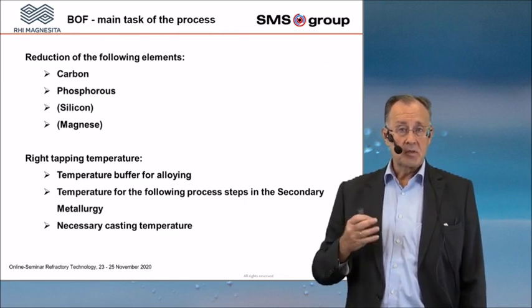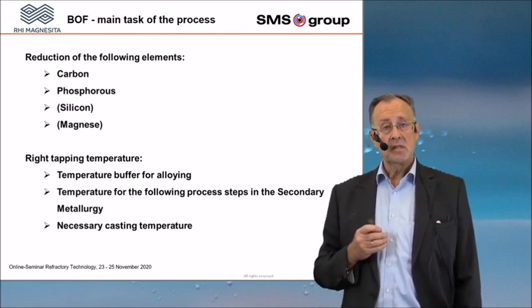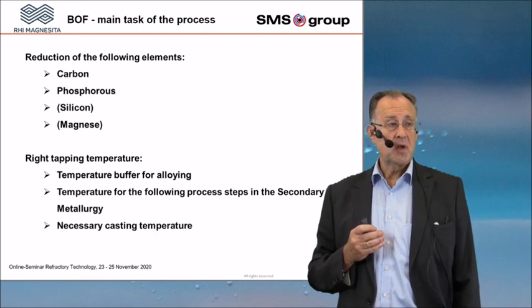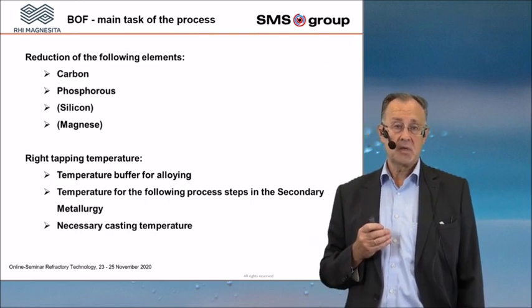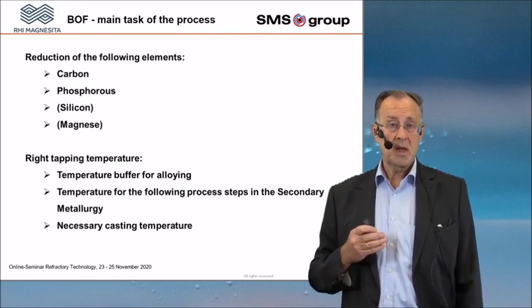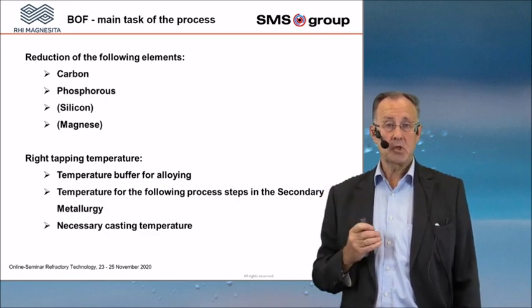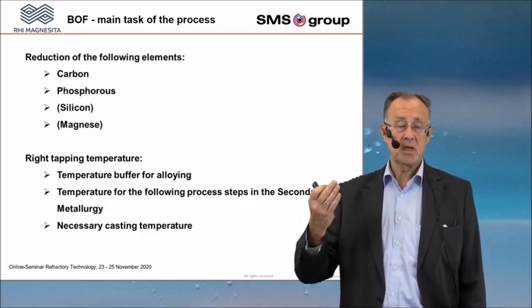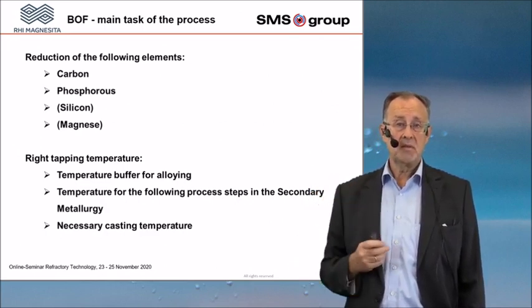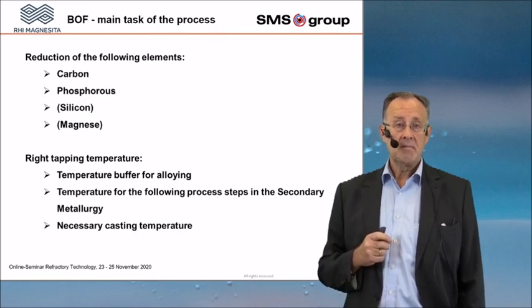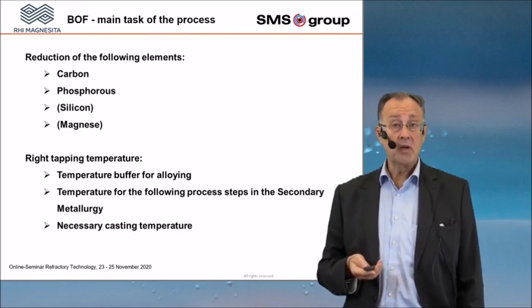But today, very often, and this is completely a change in the philosophy, you will have ladle furnaces behind the converter. So that means you can lower your tapping temperature and you can increase the temperature again, because you put the ladle in a ladle furnace for reheating of the melt.